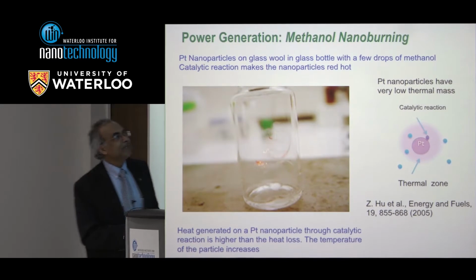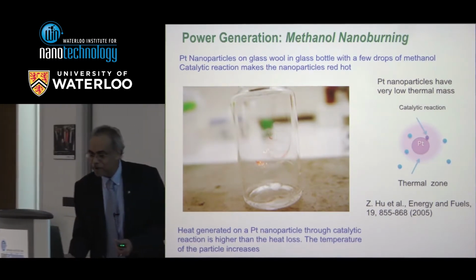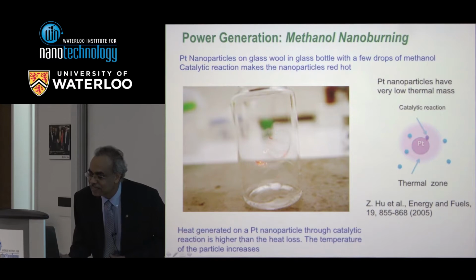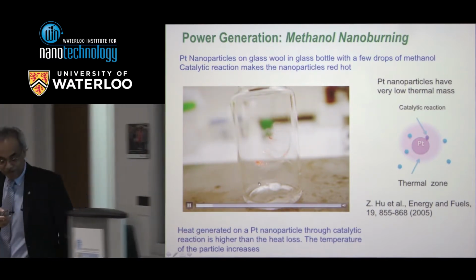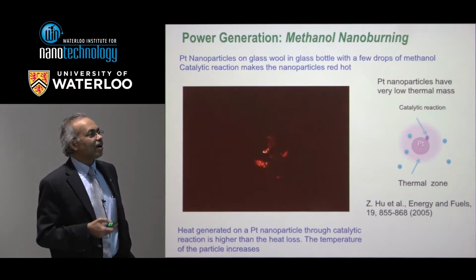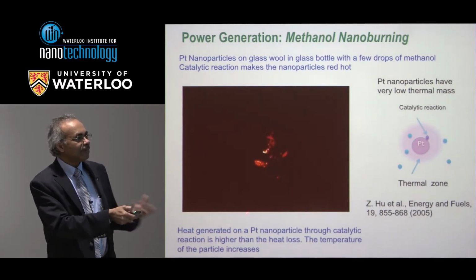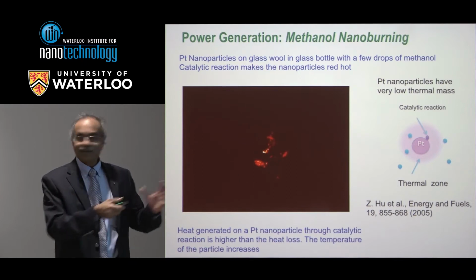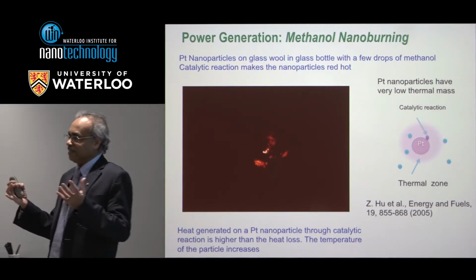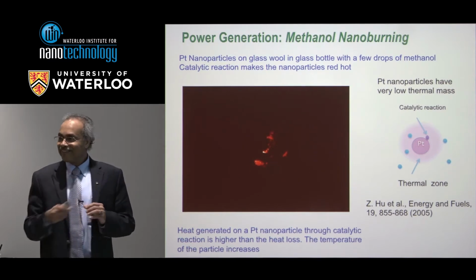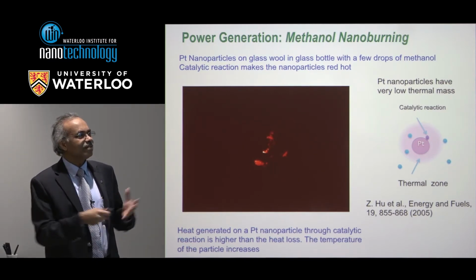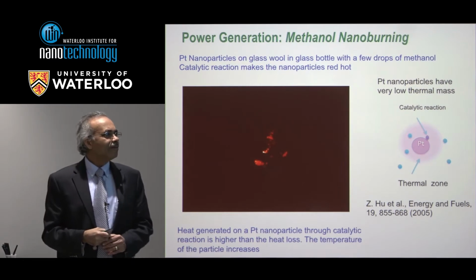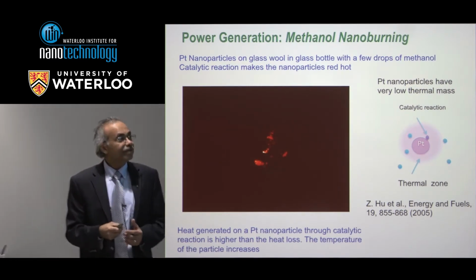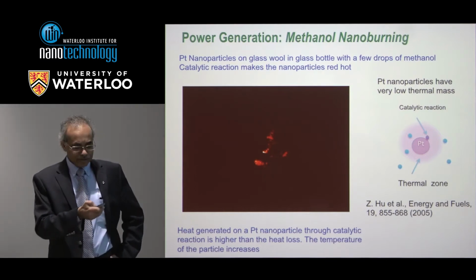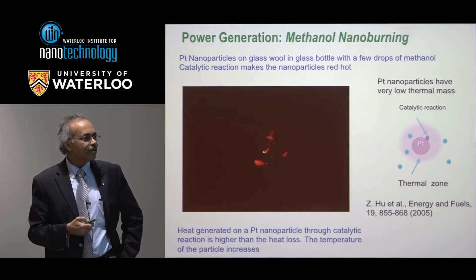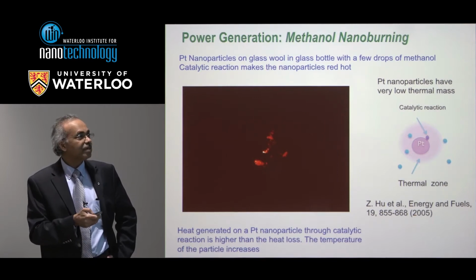So here is a video. Actually, if you take a platinum powder, platinum nanoparticle, put it in a glass wool, and then put a little bit of methanol at the bottom. What you see is that these nanoparticles will start burning. It reaches red hot, as you can see. So what happens is that platinum catalytically converts the methanol into carbon dioxide and water. This was found by Jerry Hu, who was a student of mine at Oak Ridge National Lab.